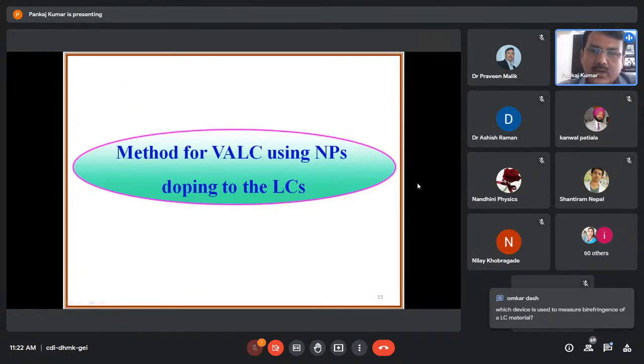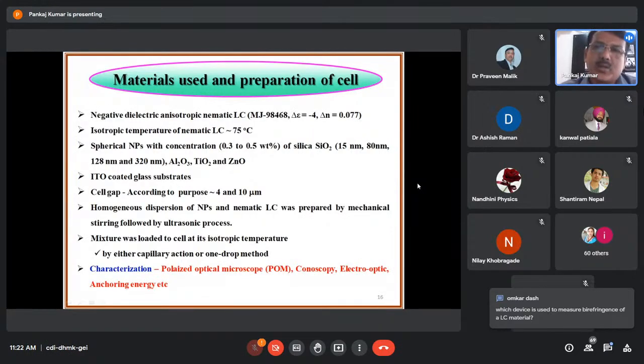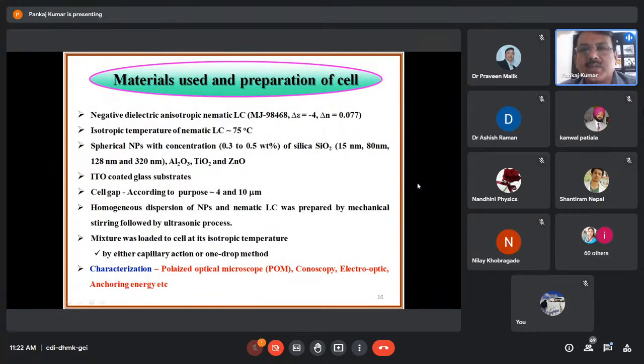Method for VALC using nanoparticles doping to the LC. Here, the materials and preparation of the cell: you can see negative dielectric anisotropy. As I told in general, for the vertical alignment mode, the negative dielectric anisotropy nematic liquid crystal is generally used. So here we use the MJ98468, which has negative dielectric anisotropy, delta epsilon is -4, and the birefringence value is 0.077. The isotropic temperature of this nematic liquid crystal was 75 degrees C.